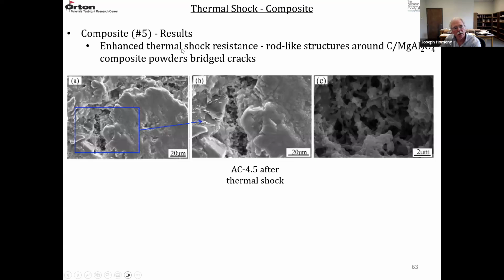And then they're also looking at the rod-like structures that are forming around these powders, these composite powders. So you can sort of see the different rod-shaped powders in this crack here, and then here's a higher magnification of some of the rod-like shapes in a crack. And then this is much higher magnification of this rod-like structure bridging in a crack.